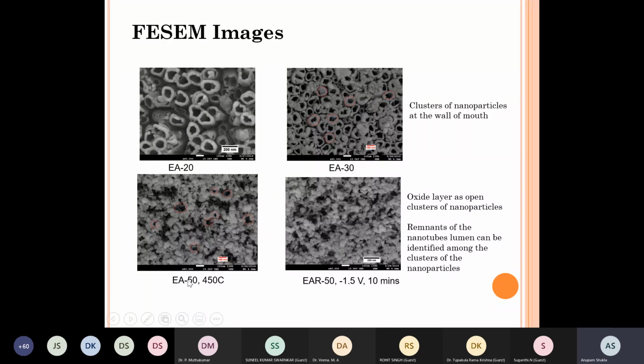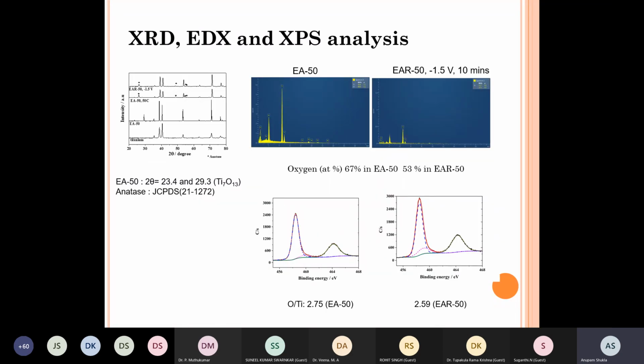And of course, what we did, one of the features is that these need to be reduced in order to improve the conductivity. Once you form titanium oxide, it has lower conductivity. So we found that if we electrochemically reduce it, the conductivity improves. And this, EAR meaning reduced, still has lumen, still has rough clusters of titanium nanoparticles around those lumens. So therefore, high surface area, straight pore structure.